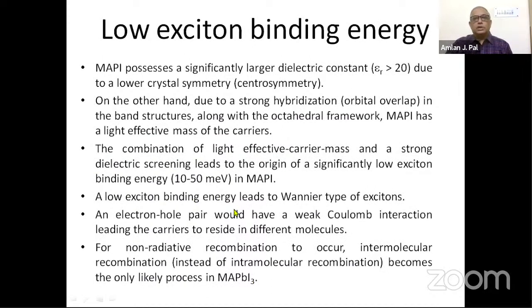In this particular material, methyl ammonium lead iodide, it possesses a large dielectric constant. What happens if the material has a large dielectric constant? Just remember Coulomb's law. Because of the large dielectric constant, the attractive force between the electron and hole will be less. Because of this lower force, it will be easier to dissociate or separate the charge carriers. The binding energies are as low as 10 to 50 milli-electron volt. At room temperature, the material can itself separate the charge carriers within the methyl ammonium lead iodide.